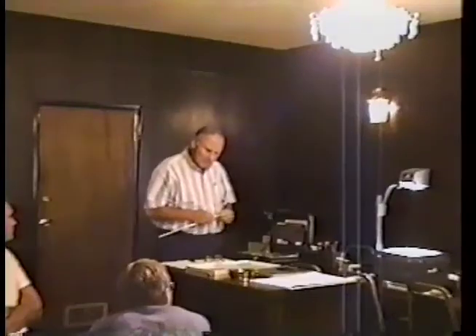Some slight changes in porosity will get you away from that chicken wire pattern into what they call a pinpoint pattern, but that's a method that's used by most of the players in this business to get the porosity. All of the control factors, temperature, amperage, and so on, they all play a part in the deplating process equally as they did in the plating process itself. So they are all important just to dissolve the chrome off that surface to establish a basis for porosity.